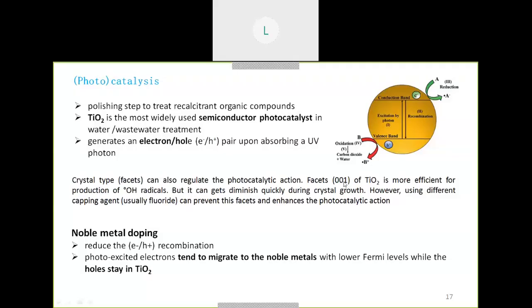How did they do it? They usually just use a capping agent, which is fluoride, and prevent the phase change, so that the hydroxyl production capacity can be maintained. Another application is where TiO2 requires UV light. If you dope it with noble metals, you can work directly in the visible region, because the electron can jump directly to the surface of the silver or gold, and the separation can be maintained and the recombination can be delayed, where other ROS can be formed.